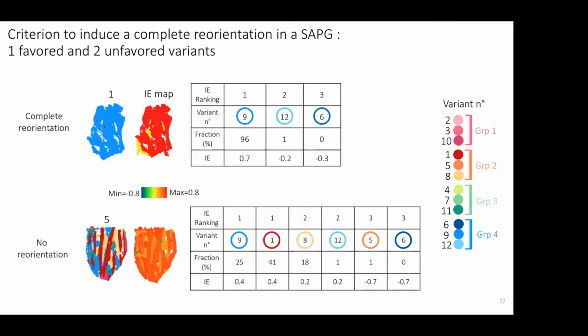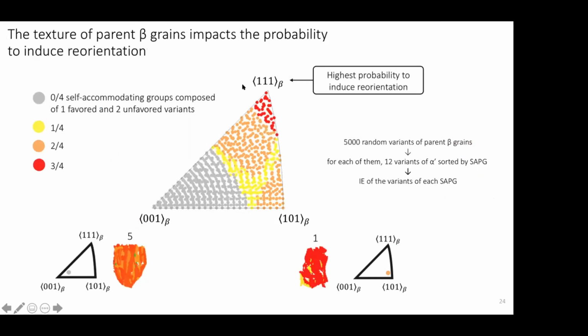That's the only case where you can find a complete reorientation at the scale of a self-accommodating group. Based on that last criterion, we did a theoretical study, and that's the result. I'm going to explain the steps of this theoretical study. We took 5,000 random variants of parent beta grains, so different orientations of the beta grains. From each orientation, we computed the 12 variants that can be created from this beta, and we sorted them by self-accommodating groups. On each self-accommodating group, we computed the interaction energy to see whether or not we are in the case of one variant favored and two unfavored. And we counted the number of groups that respect this criterion. As a result, we have from 0 to 3 groups that respect this criterion.